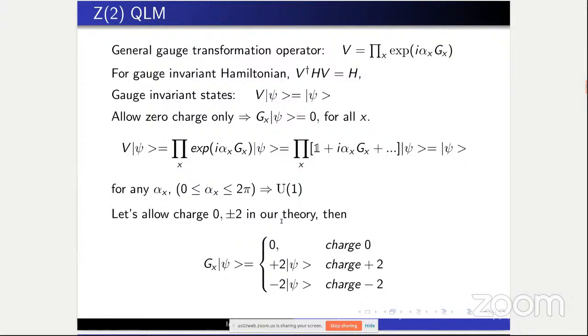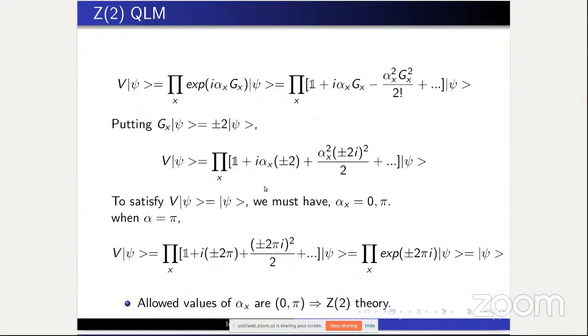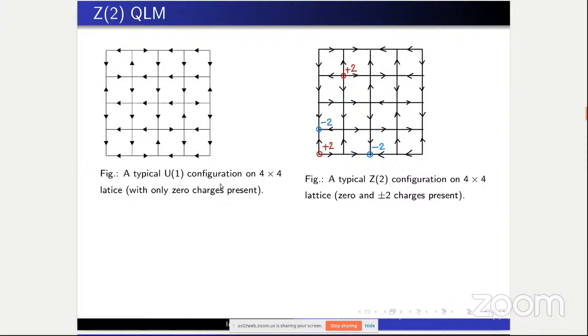Now, if we allow charges plus minus 2 along with charge 0, then there are 3 possibilities: G_x equals 0 for charge 0, G_x equals plus 2 psi for charge plus 2, and minus 2 psi for charge minus 2. Then one can show that the only possible values of alpha_x are 0 and pi, for which this relation V psi equals psi is satisfied. So the theory effectively becomes a Z2 theory. This is a typical U(1) configuration on a 4x4 lattice, and this is a typical Z2 configuration on a 4x4 lattice, where there are plus minus 2 charges along with 0 charges.